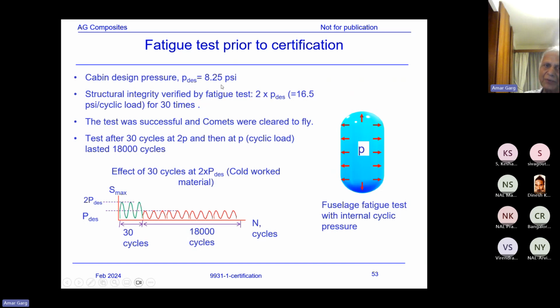But what happened when the testing was done? The design pressure was 8.25 psi, for which the fuselage was designed. And they tested at 16.5 psi per cycle load. That is, they doubled the pressure for the fatigue loading, thinking that if they doubled the pressure, then they would have to test only a few cycles, and then it would be okay for certification. And the Comets were certified based on that criterion.